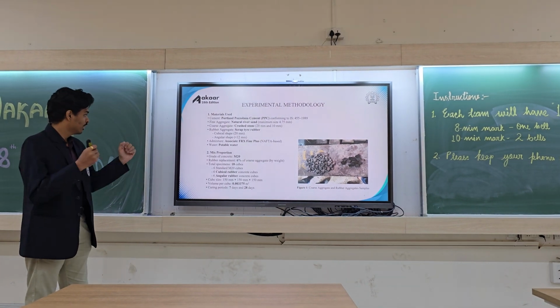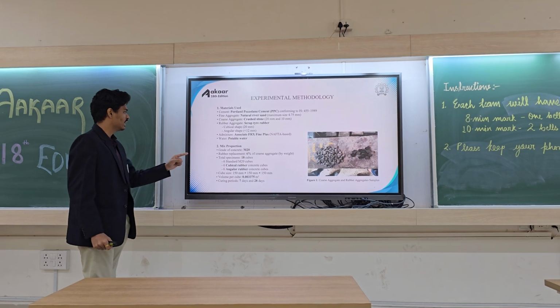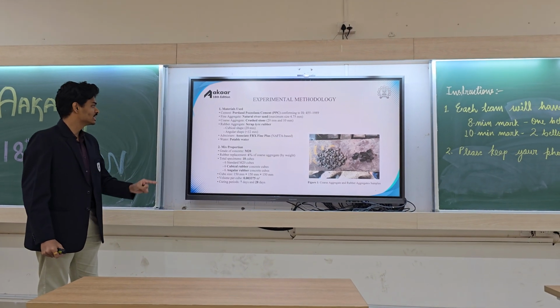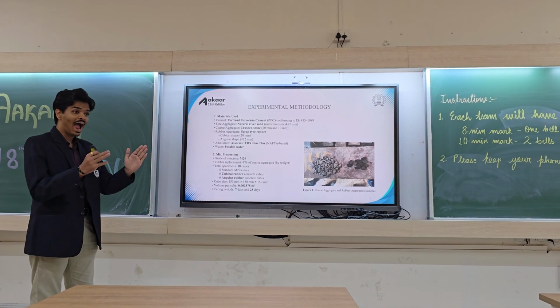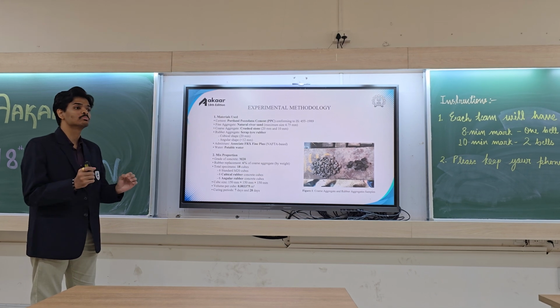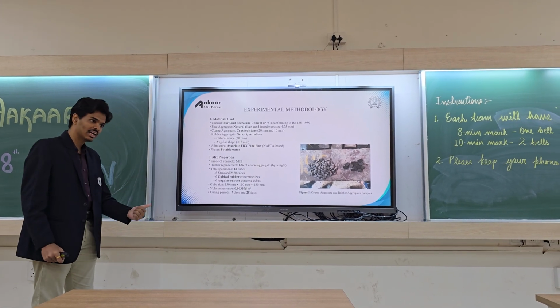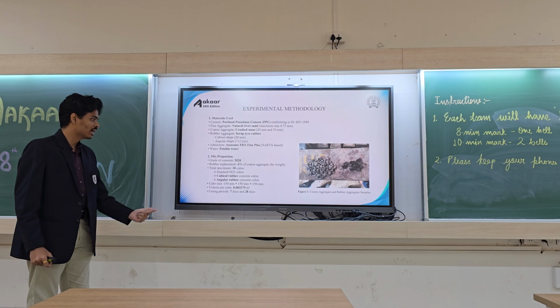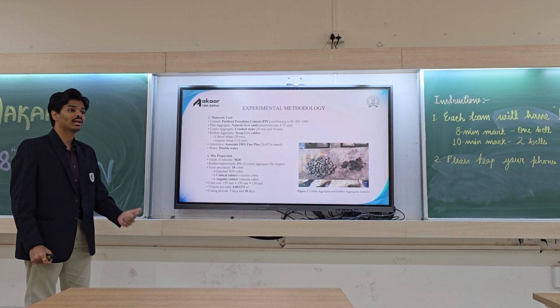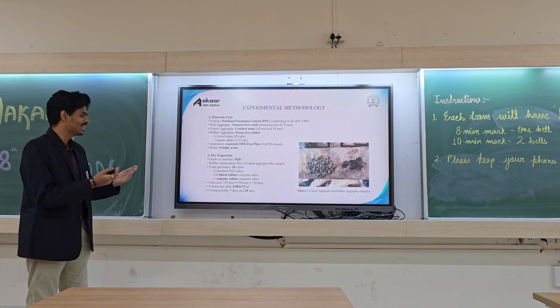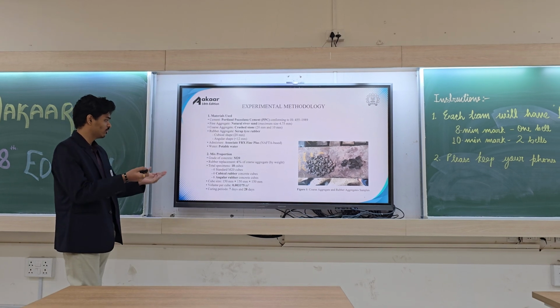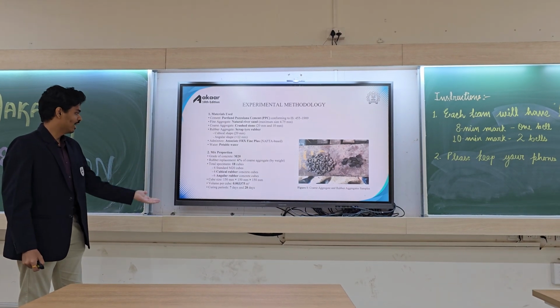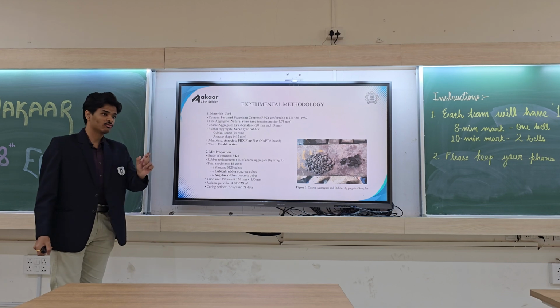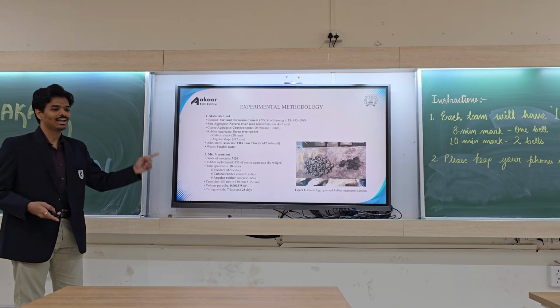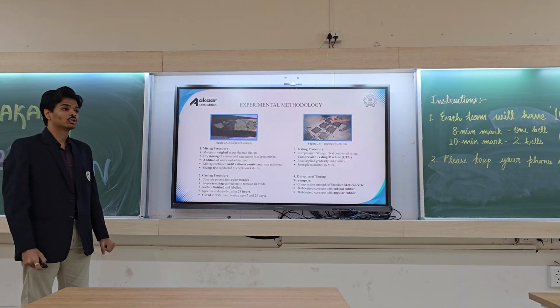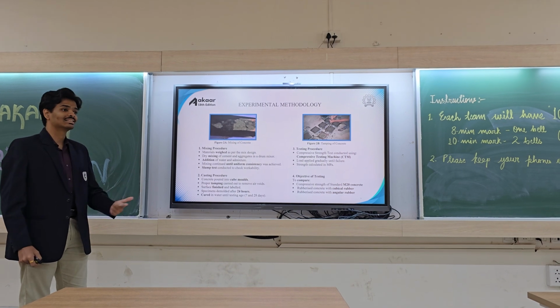The mix design is as follows: grade of concrete M20, rubber replacement 6% of coarse aggregates, and a total of 18 cube specimens were cast by us. 6 of standard M20 concrete, 6 of cubical rubber concrete cubes, 6 of angular rubber concrete cubes. Cube size standard 150 by 150 by 150 mm, volume 0.003375 m3, and curing period 7 and 28 days. The experimental methodology covered mixing, casting and testing.